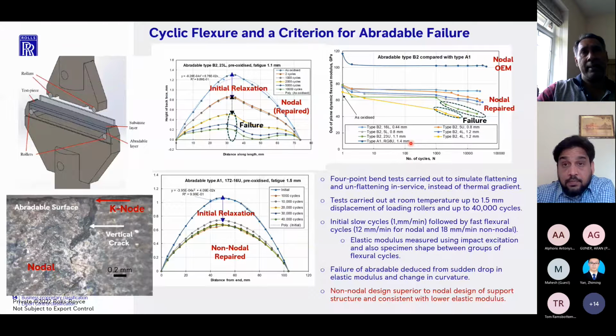Basically what you can see is that when failure of the abradable occurs in the nodal design, there's a sudden drop in the elastic modulus. As long as there is no real damage accumulated within the abradable, the elastic modulus is more or less constant. But beyond a certain displacement or a certain number of cycles, when the abradable begins to develop cracks, there is a sudden drop in the elastic modulus. So you can ascertain the number of cycles for a given displacement, or the displacement for a given number of cycles, when the abradable begins to fail.